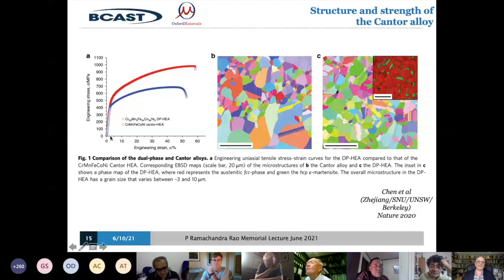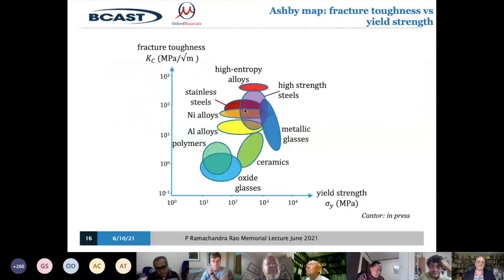And the Cantor alloys show that, and all of the FCC alloys do. In fact, it turns out that they're the best. So here's what's called an Ashby map, fracture toughness, resistance to fracture and strength. And here are different materials, polymers, oxide, glasses, ceramics, and so on, different metals, high strength steels. Here are the high entropy alloys right at the top with the best fracture resistance and as good yield strength as, better nowadays than even the best.